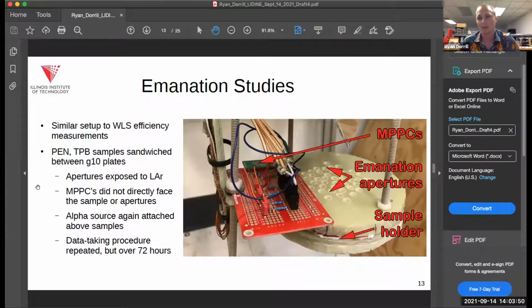So we wanted to test PEN similar to how TPB had been tested with Jonathan's group before, and see if it seemed to emanate as well and have rising count rates. You can see the setup here on the right, where we had G10 holders for our samples with small apertures in them. And note that this sample holder was not directly facing the SiPMs on the left side here.